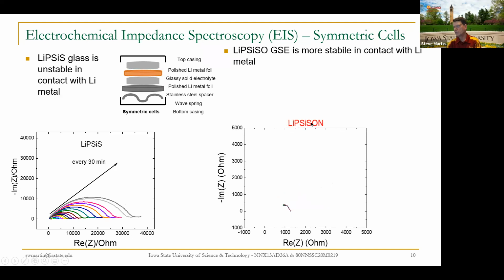And then when we go to the oxysulfide nitride, notice the scale is the same, 5,000. Let me go backwards. Notice that scale is 5,000. Look how small the arc is. The arc is small because the conductivity is so much higher, and it doesn't change at all with time. So this shows us that the oxysulfide nitride chemistry is very stable to lithium. What does that mean? You could put your battery together, let it sit there for 5 or 10 years and it would be stable, and your battery would work when you needed it to. So showing that the glass is stable to lithium metal means we can use the glass as a solid electrolyte in a lithium metal battery.